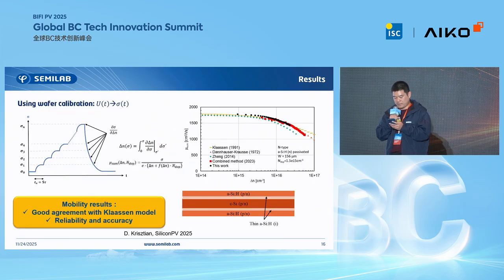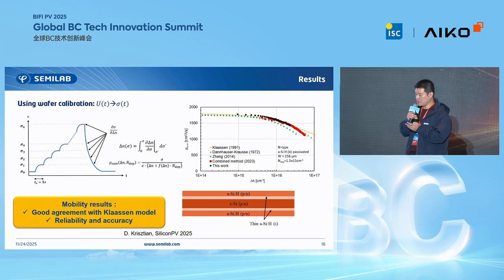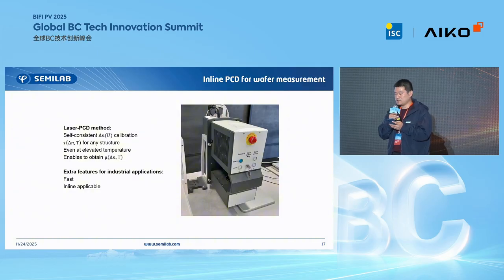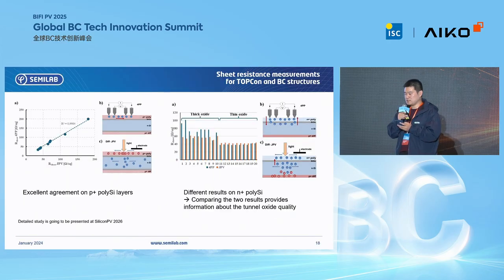In the next page, we prove the accuracy of our model using the mobility data. We confirm the accuracy of this model by calculating the mobility of excess carriers using this method. Results on these symmetric amorphous silicon passivated wafers agree very well with literature data and also align very well with our previous results using a more complex and time-consuming method. I would like to mention that a single carrier lifetime measurement like this takes less than 1 second. This is a prototype of our laser PCD lifetime measurement system equipped with the new evaluation model. It is designed for inline use and will be commercially ready in 2026.